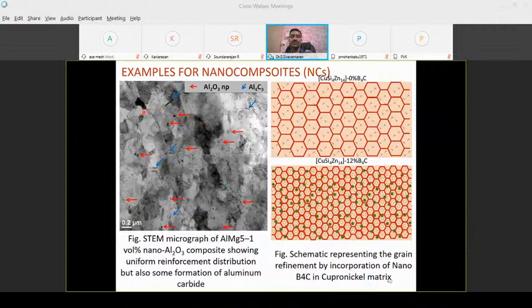So when we see this microstructure, almost all the nanoparticles and nanofibers are distributed uniformly. Obviously, we can obtain improved properties. And further, when we add a percentage of nanoparticles over any metal during synthesizing, especially with high energy ball milling, the grain size will decrease. You know very well, the conventional material has very big grains, maybe 1 to 2 micrometers. When we want to reduce the grain size, maybe to 100 nanometers or 60 nanometers, or if you incorporate some ceramic particles, the grain size will be around 10 or 15 nanometers. My point is, by incorporating nano reinforcements, the grain size of the bulk metal can be decreased.